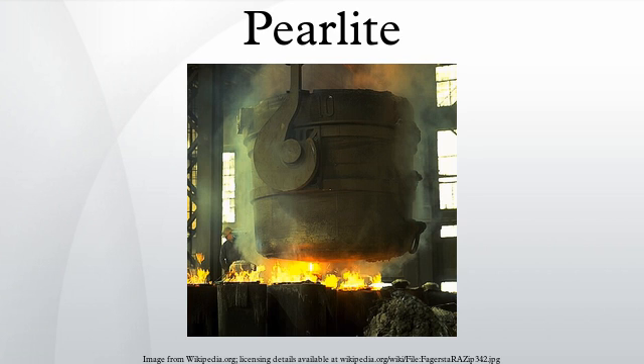High degrees of wire drawing lead to pearlitic wires with yield strengths of several gigapascals, making pearlite one of the strongest structural bulk materials on earth. Some hypereutectoid pearlitic steel wires, when cold wire drawn to true strains above 5, can even show a maximum tensile strength above 6 GPa.